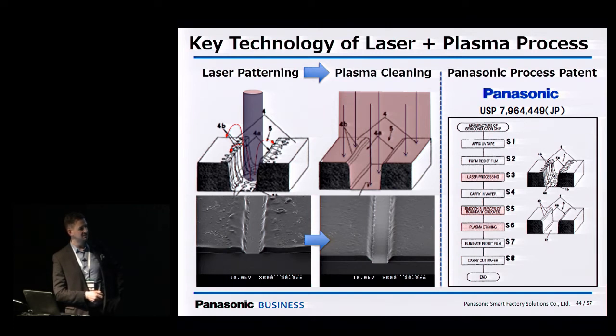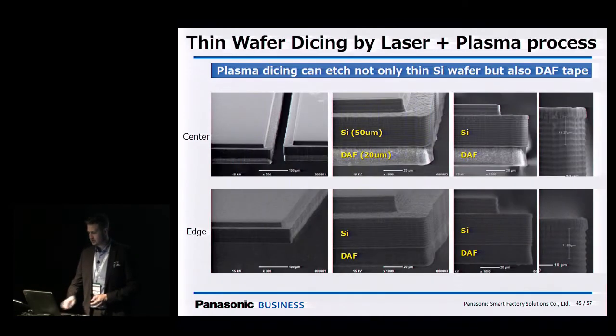This is just a mask, so it doesn't matter. What's more important is the edge quality here, because if it's exposed like this, it will etch vertically down and make a rather undulating side quality. But if you run our plasma cleaning step inside the same chamber, it cleans things up nicely. And then this is just an example of us being able to dice with die-attach film.